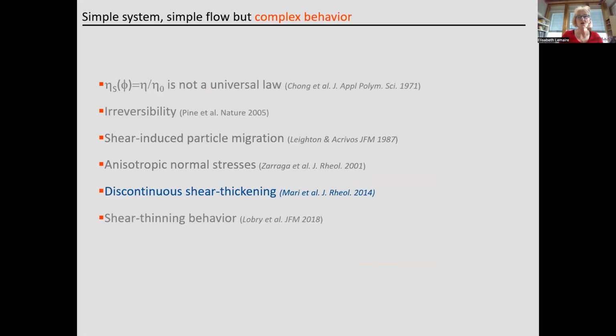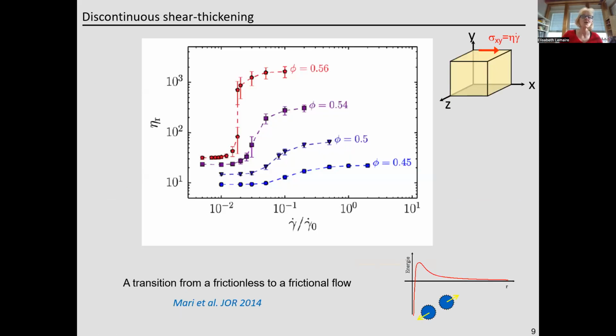Among the non-Newtonian behaviors, we also have discontinuous shear thickening. This behavior is quite popular. I'm quite sure that you know the behavior of corn starch suspensions. So the discontinuous shear thickening means that the viscosity is low at low shear rate or at low shear stress. And when you increase the shear rate or the shear stress, then you observe an abrupt increase of the viscosity.